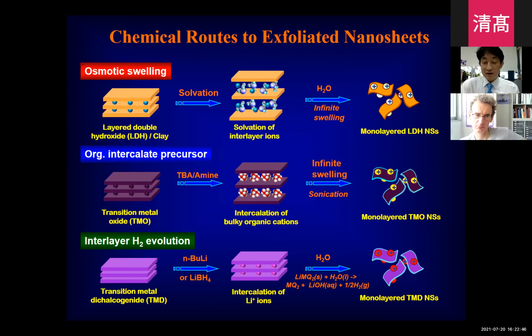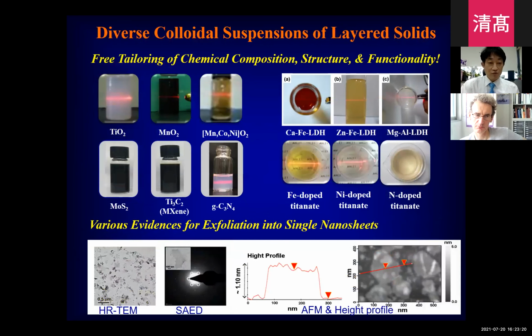In case of TMD, like molybdenum sulfide, there's no exchange of the interlayer ionic species. So at first, we have to intercalate the lithium ion by a chemical or electrochemical way, and then react with water. In that way, we can induce the hydroxylation of the intercalated lithium ion. It leads to the evolution of hydrogen gas, so it causes a drastic expansion of volume. So we can separate the TMD lattice into monolayered nanosheets. We can synthesize many kinds of inorganic nanosheets. We can somewhat tune the chemical composition by adopting chemically substituted host materials.